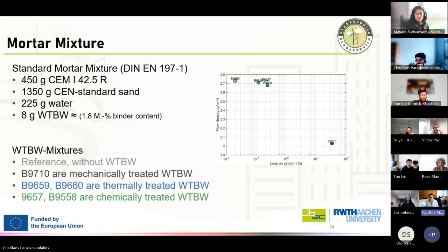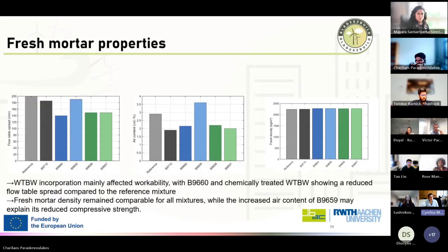So if we go to the next slide, please, you will see the results of the fresh mortar properties. What we did is, for once, the flow table spread, which is the consistency measurement. We did some air content measurement, and we also did the measurement on the density. Just starting from the right-hand side, we don't have any measurable change in the density. With this small amount of fibers, this is something that we thought shouldn't change that much.